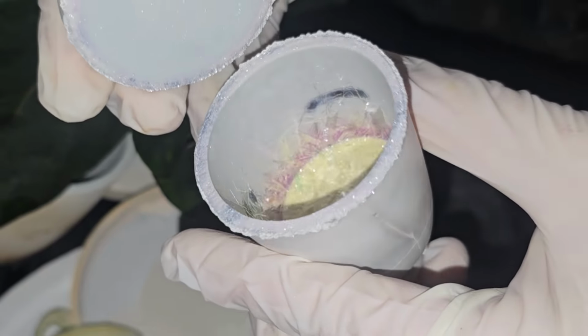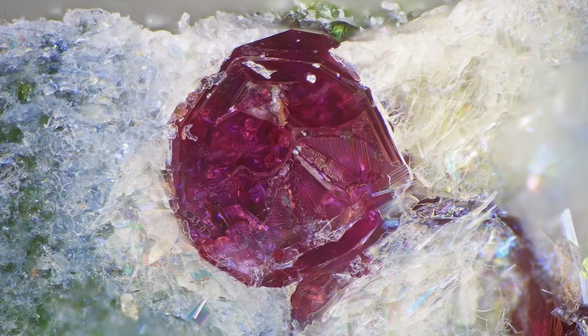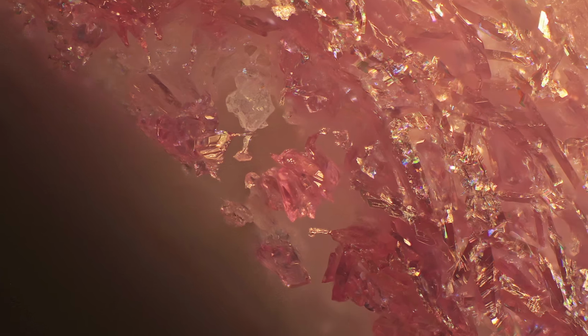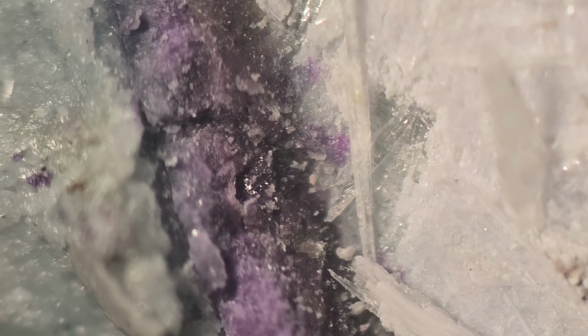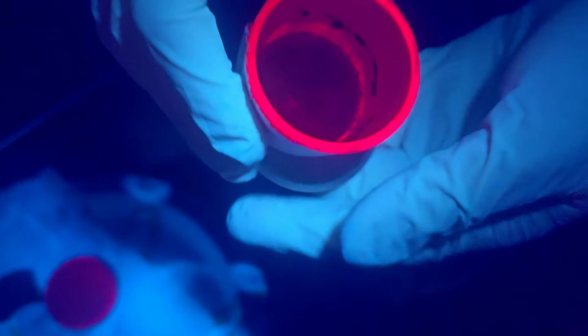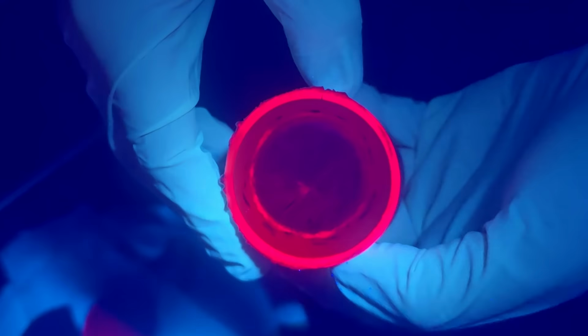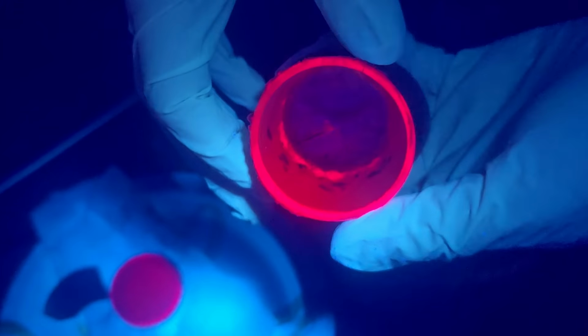I was ecstatic to see these, but my happiness was short-lived. Sure, there were rubies up to 1 millimeter long, but they only formed at the edges of the crucible. Under the surface, there was just an opaque ruby lump. It seems that since the crucible is made up of tiny crystals of sapphire, the ruby just wants to grow everywhere all at once. So it was back to eBay to look for alternatives.